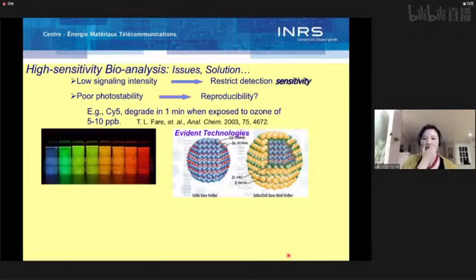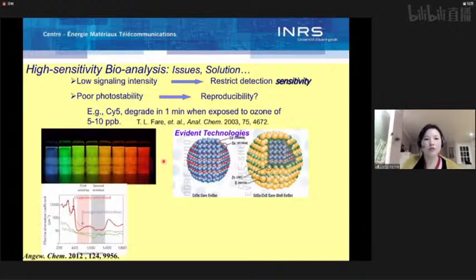On the other hand, luminescence can also be very interesting for biomedical applications. In this regard, quantum dots are very promising. As compared to traditional dye molecules, quantum dots show higher signal intensity and better photostability. So they allow more sensitive photoluminescence detection of biospecies. And from this figure, you can see that for bioimaging, there are two wavelength ranges where skin, fat, and blood absorb less and also scatter less. It means if we do bioimaging in these two biological windows, we can have a higher signal-to-noise ratio, and therefore we can get deep tissue imaging.